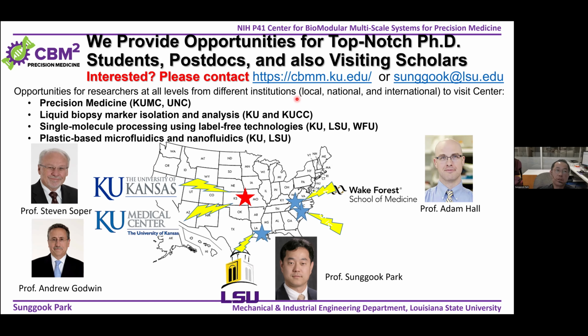I think we really haven't addressed that a lot in this seminar, but the one device I showed has a nanopore depth over 20 nanometers. Now you put the cover plate on top of that, and then do thermal fusion bonding. Thermal fusion bonding intrinsically involves fusion of polymer chains from the substrate and cover plate, which will reduce the size of the pore. So after the thermal fusion bonding, you can control the final in-plane nanopore size. Once we measure the open pore current and estimate the pore size, it can go down to a few nanometers, 2 to 3 nanometers easily.